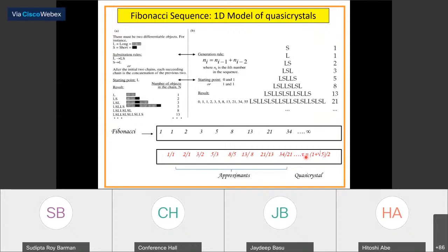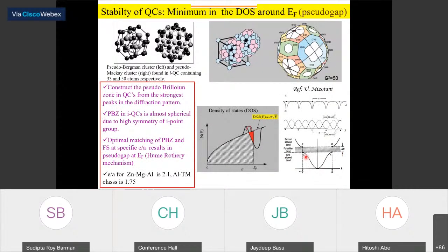So the quasicrystals have been related to the minimum found around the DOS near the Fermi level, which has been called a pseudo gap. This has been related to a perfect matching: the pseudo gap arises because of the Brillouin zone, and the matching between the pseudo Brillouin zone and the Fermi surface at specific e/a ratios. And this is known as the Hume-Rothery mechanism. And it is related to the clusters, which all have very close to spherical symmetry.